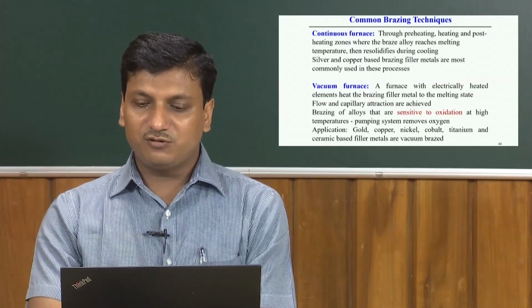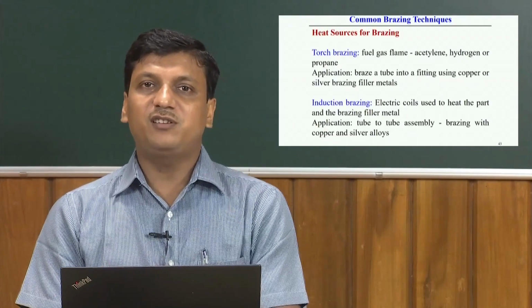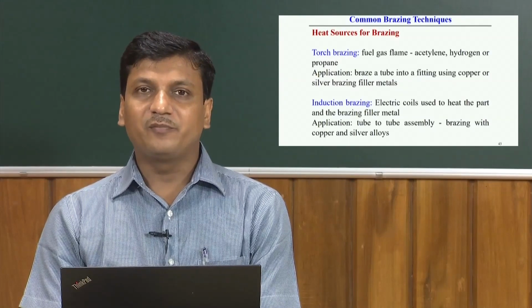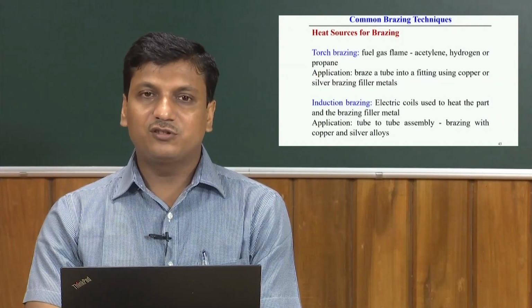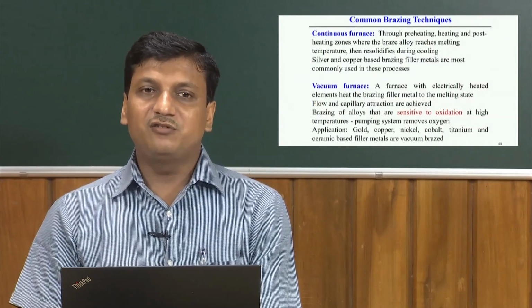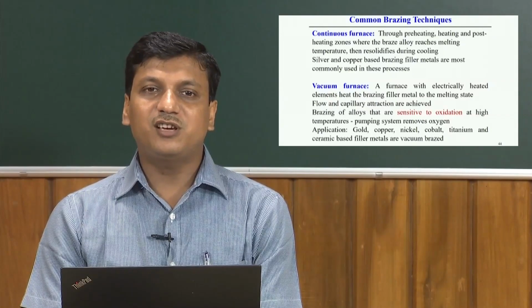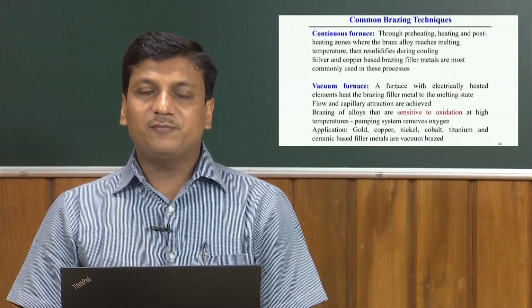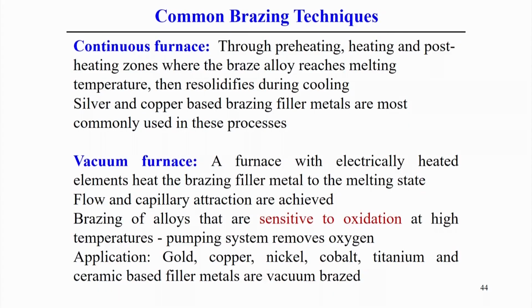If we consider all these different brazing techniques, the simplest application is torch brazing. Induction brazing is a more controlled approach where we can control the temperature. Then continuous furnace and vacuum furnace are also other brazing techniques. The continuous furnace is open to air, but we typically follow the sequence of preheating, heating and post-heating zones, which are controlled using the continuous furnace. The vacuum furnace is a simple way to avoid contamination from the surrounding atmosphere during the process. In this case, generally a vacuum furnace is required.